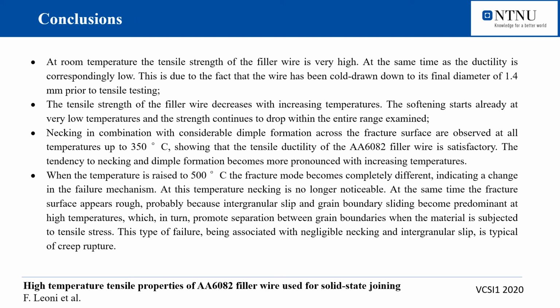The following conclusions can be drawn from the investigation that has been carried out. At room temperature, the tensile strength of the filler wire is very high. At the same time, the ductility is correspondingly low, and this is due to the fact that the wire has been cold drawn down to its final diameter of 1.4 mm prior to the tensile testing. The tensile strength of the filler wire decreases with increasing temperature. The softening starts already at a very low temperature and the strength continues to drop within the entire range examined.